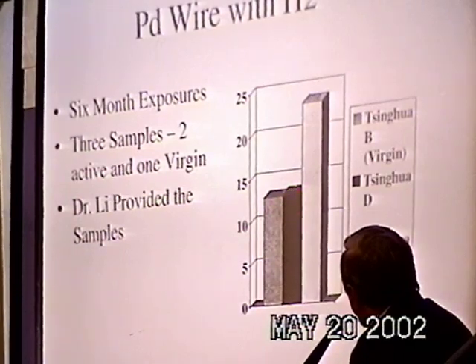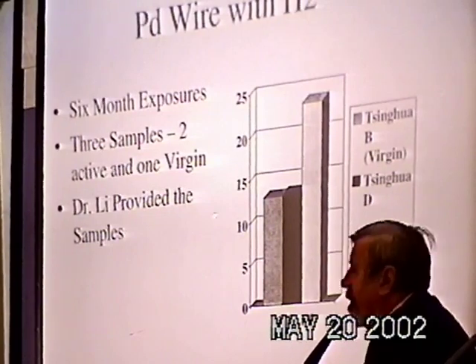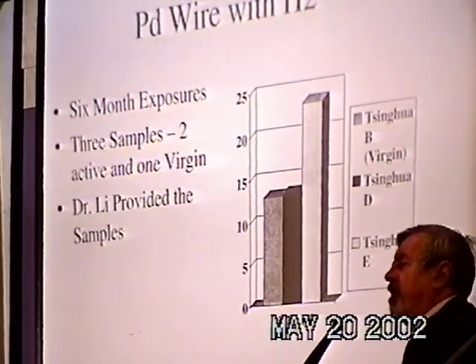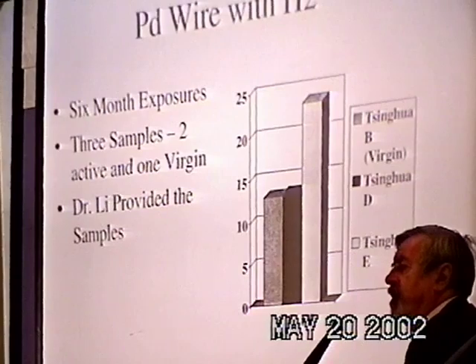D didn't seem to be very much of an active sample as far as I was concerned with lithium 7-6, but E was a factor of 2 increase or depletion in a 7-to-6 ratio. So I got this fairly early in the game, and was quite encouraged by that, assuming that it might turn out to be really a barn burner. But as usual, it's not quite that.